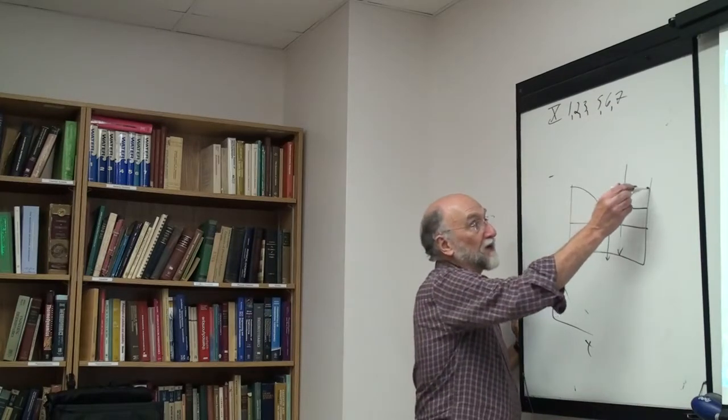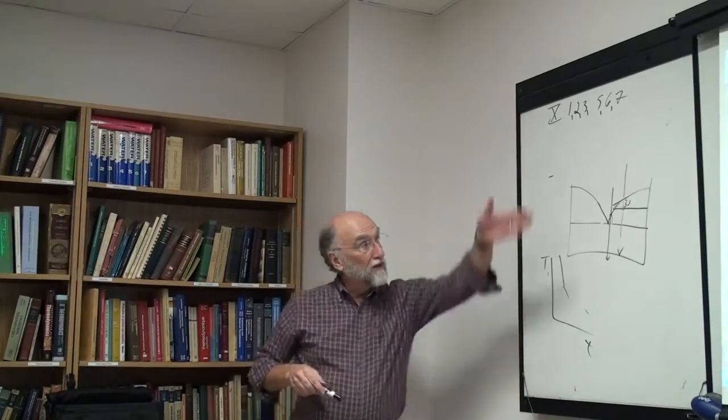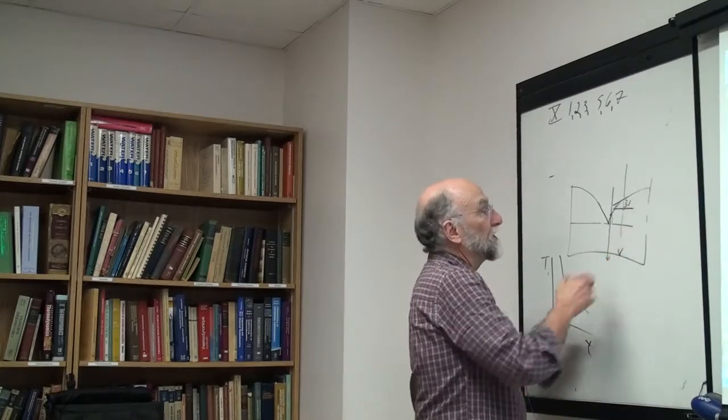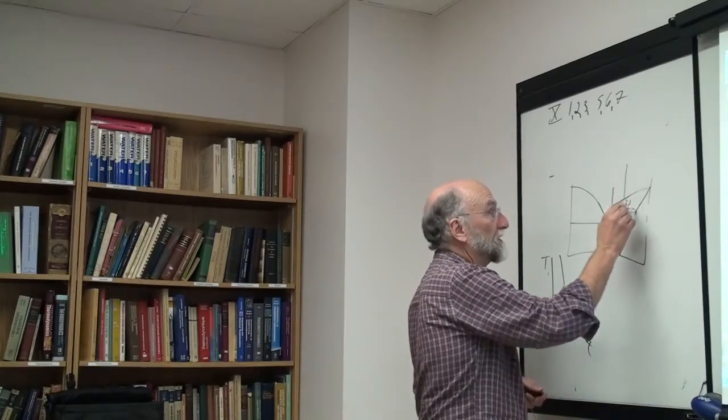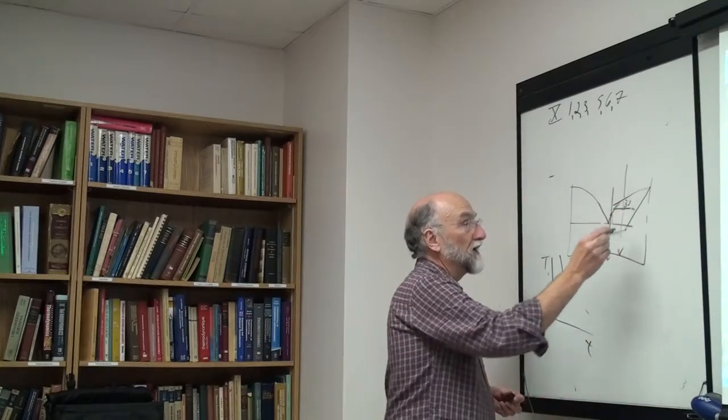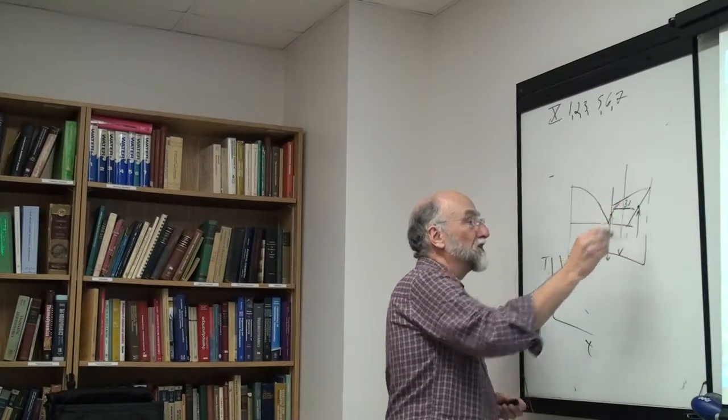So a flat liquidus is generally very easy to measure by a cooling curve. A steep liquidus is very difficult to measure by a cooling curve. Soliduses are very, very difficult to measure by a cooling curve. People will try to do heating curves to get the solidus and the eutectic. A heating curve is absolutely no good for a liquidus. It's not too bad for a solidus.